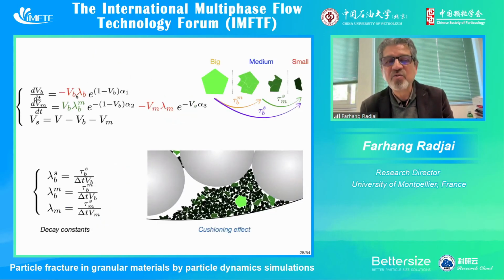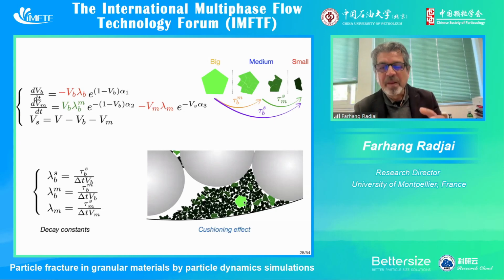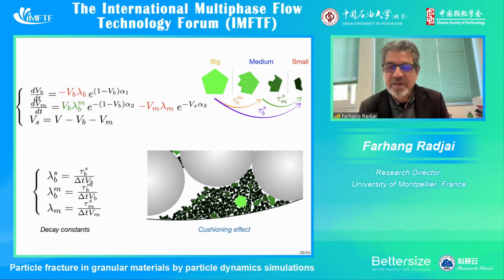So we have basically 2 equations, but also we have the conservation of volume. And what is interesting here is that for this model, we had to include a term to account for the cushioning effect. So in a way, when you have a big particle with many small particles around it, the stresses are not transmitted the same way as when you have a particle like here between a ball and the wall. So we have to account for the cushioning effect of smaller particles. And these are these terms which have been introduced here.